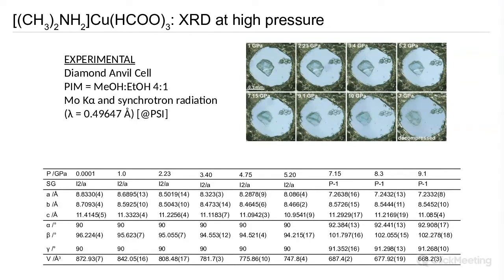So given this, high pressure X-ray diffraction studies were performed in diamond anvil cells on the dimethylammonium copper formate system. Here we've got these nice pictures to show the sample well loaded within the gasket of the diamond anvil cell. And these measurements were done by Michael and colleagues at PSI. So what was observed?